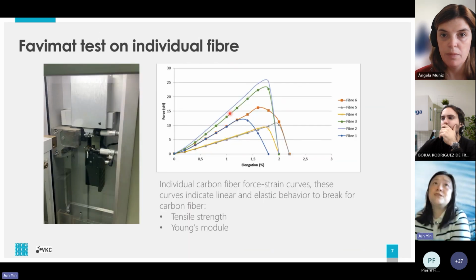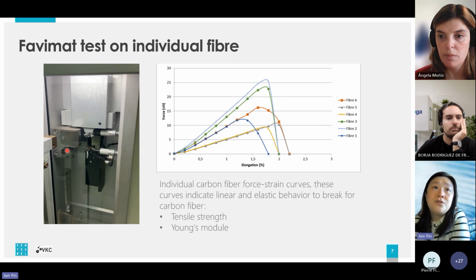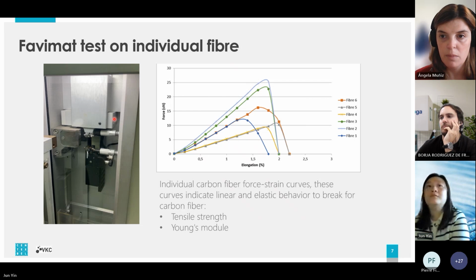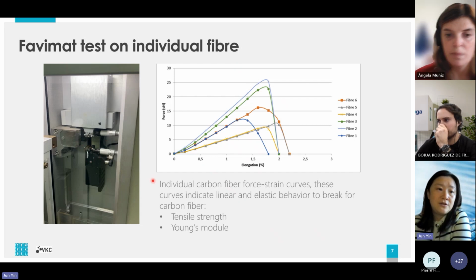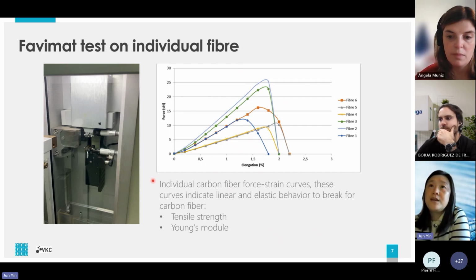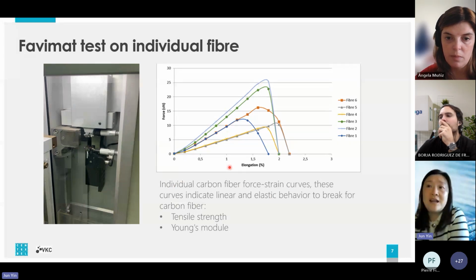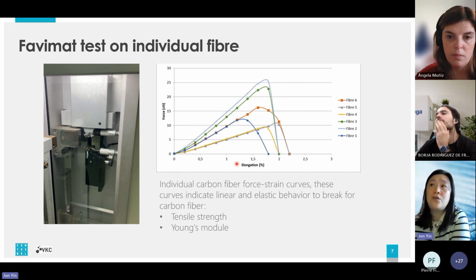So first, using the Favimat test, maybe I can show a small video. It doesn't work. So, okay, the fiber is suspended on these two heads of this machine. Then it applies force to make this tensile test. So we can get the force and strain curves. We can see that at the first stage of these curves, it indicates a linear and elastic behavior to break for these carbon fibers. So we can use the slope of this curve to estimate the tensile stress and Young's modulus.